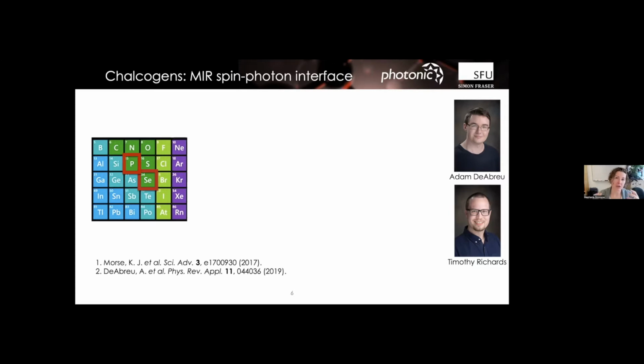Because of course, if you want to have a good spin photon interface, that optical interface is the thing that makes or breaks your technology. So we went hunting for something that looked to have potentially a stronger photonic interaction. And we started by looking at selenium. And selenium is a lot like phosphorus. And you can use the periodic table as a rough guide here. So the reason why phosphorus gives you an unpaired electron, a good spin to use as a spin qubit in silicon, is that it takes the place of a silicon atom, and it has one extra electron by virtue of being in the next column over. So it's very much like a hydrogen atom.